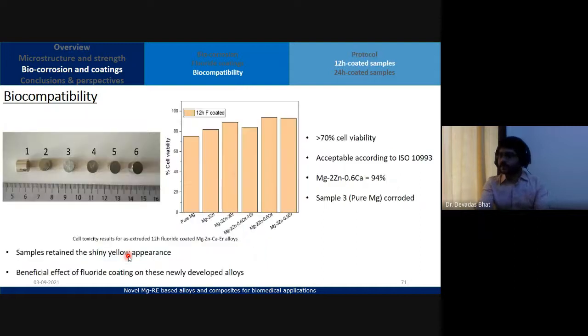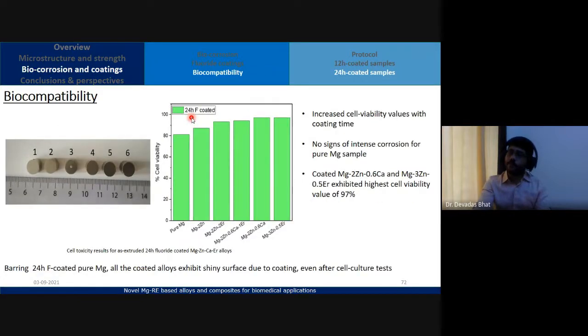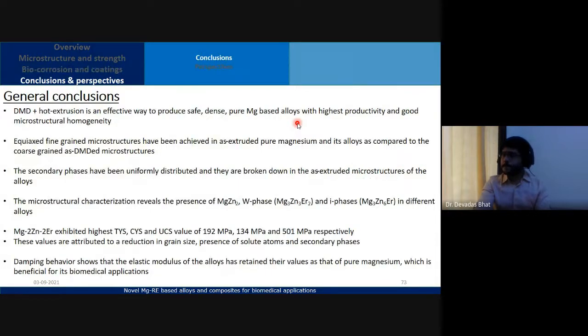Okay, so the ISO 10993 tells us that anything at and above 70% is acceptable. So among all the samples, we could find acceptable values, certainly high for a few alloys. And you see this is the pure magnesium, whereas all others are fairly good. Now these are the coated samples, fluoride coated samples. So this is 12-hour dip coating. If we go for 24-hour dip coating, you can see an increase in the viability. Okay, a few conclusions here.